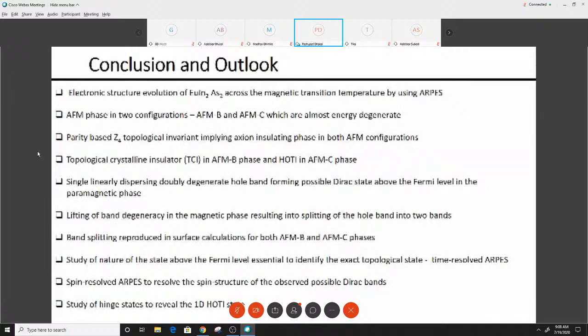Our surface measurements showed the splitting of the hole band in the vicinity of the Fermi level, going from the paramagnetic to the antiferromagnetic phase, caused by the lifting of the band degeneracy. Band splittings are reproduced in both AFMB and AFMC phases. Therefore, in order to identify the exact topological state of EuIn2As2, we need to study the nature of the states above the Fermi level by using time-resolved measurements.